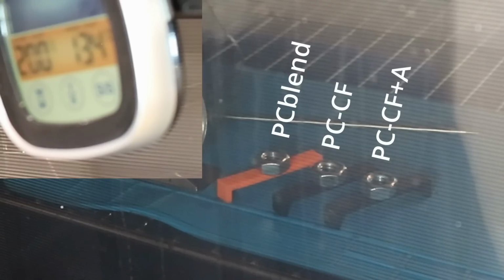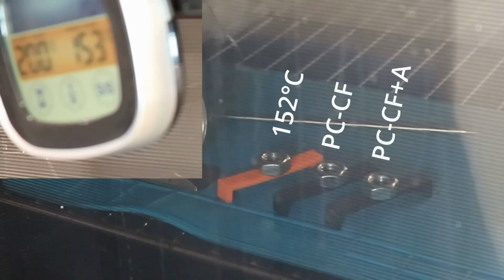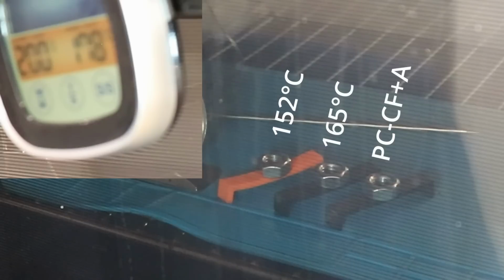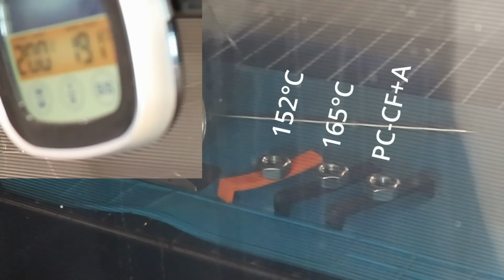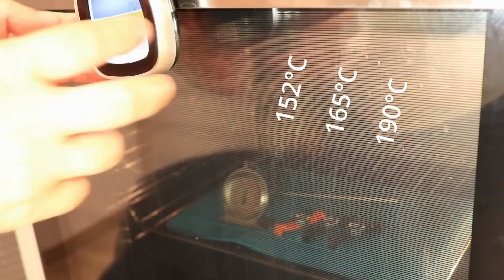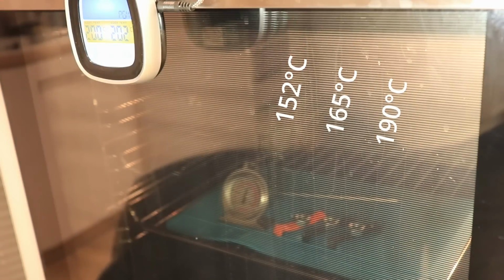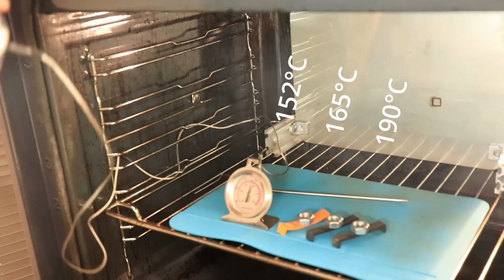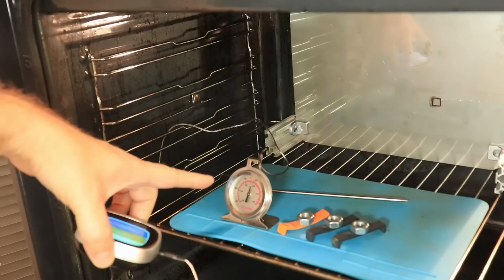And you will see it was very hard to notice the deformation moment, even with frame-by-frame analyzing. But you will see in a few seconds the final result, and the deformation is obvious. Approximately at 150 degrees Celsius, I noticed the first deformation on the PC blend, and maybe 10 or 15 degrees later the carbon fiber, and again later the annealed version. So I stopped the experiment here. It reached 200 degrees Celsius, and this one has a small delay.